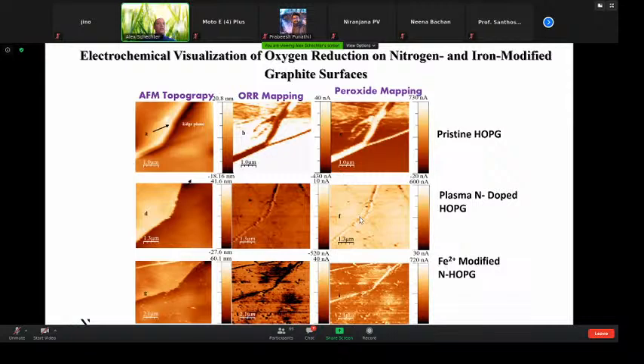And the answer is that for measuring the product, we're using larger electrodes. We're using a larger counter electrode. We're not using the tip. For oxygen reduction, we're using the tip as a counter electrode to probe exactly above that, while for the peroxide, we're only sensing. So we're not sensing 100% of the peroxide. We're sensing part of it, but even that part of it that is generated by a larger counter electrode gives us higher current.